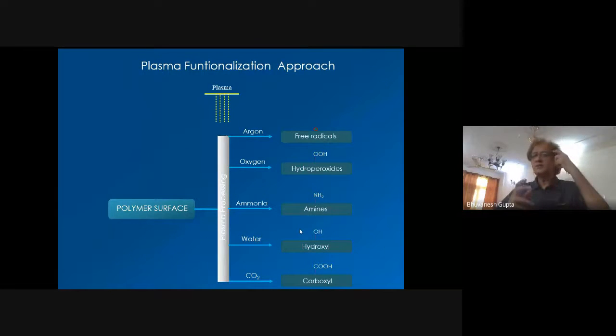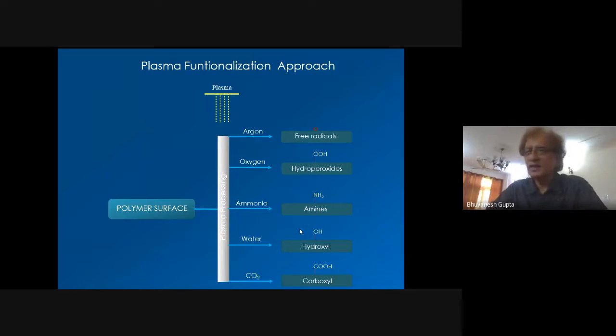So what happens is plasma, very interesting, and I like to tell you these things especially because, see, if you have the plasma, argon as the carrier gas, you get the free radicals. If you have oxygen, you can get hydroxyl groups, you can get hydroperoxide groups. If you have ammonia, you can get amino groups. If you have steam, water as the vapor, you can get hydroxyl groups. And if you have carbon dioxide, you can get carboxyl.